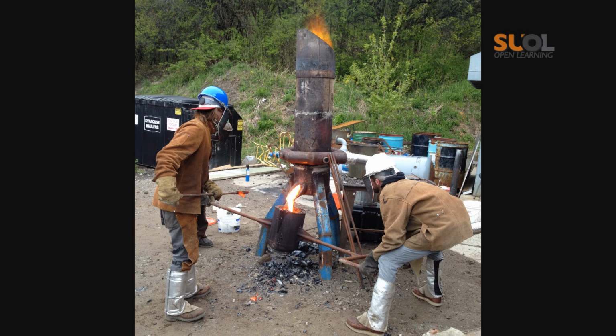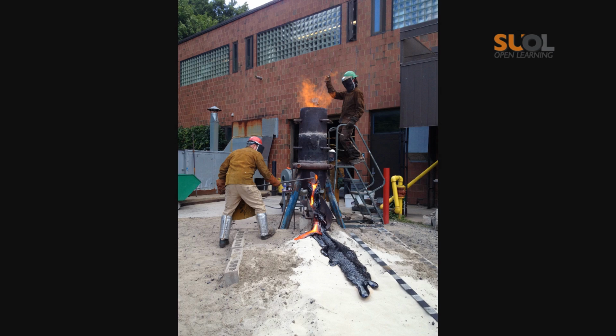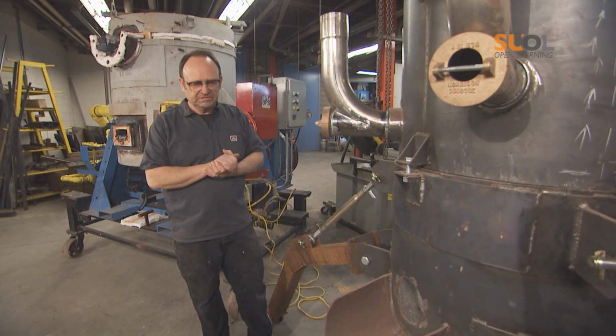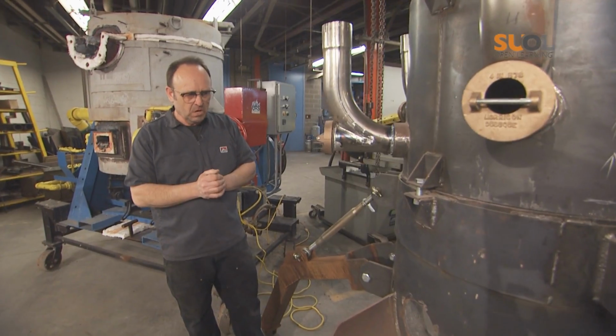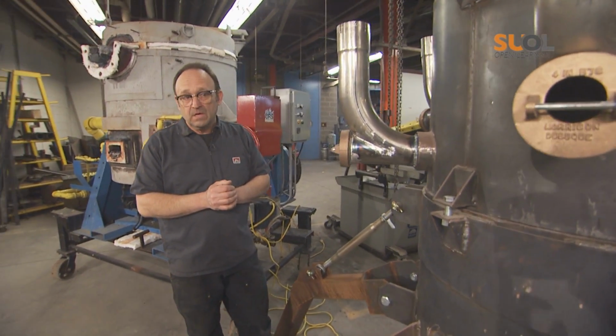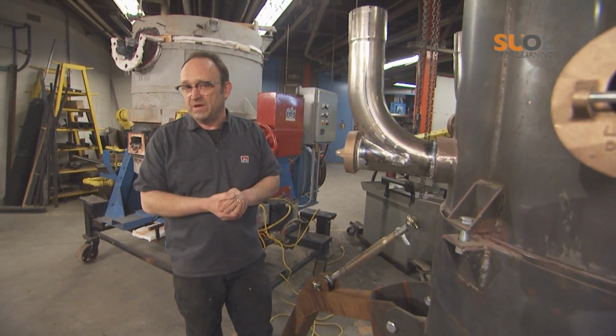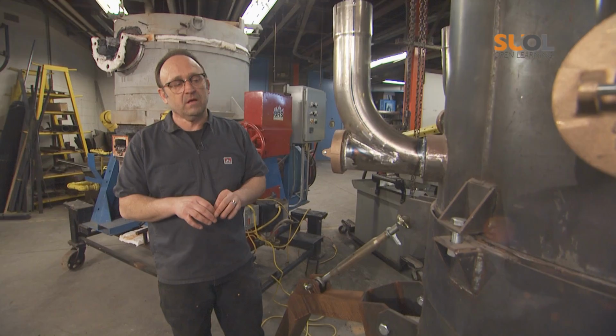And we weren't sure at first when we tested it how it would work. We didn't know if it'd be a continuous flowing thing or if the bottom would just fill up and it would be similar to the gas-fired furnace. In June of 2012, we had our first test firing of, as I said, much smaller, and it flowed continuously for 45 minutes and put out 600 pounds.